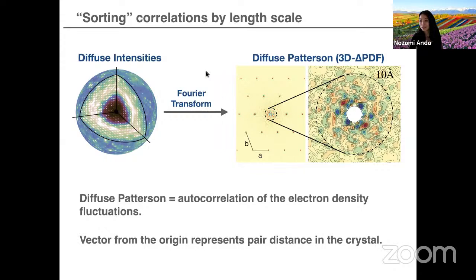And when you do that, you convert the intensities into what is known as a Patterson function. In the materials field, it's called a 3D delta PDF. But essentially, we're going from reciprocal space into real space. And if we zoom in near the origin, the way to understand this plot is that any vector starting from the origin is telling us about the correlations along that direction and in that length scale.